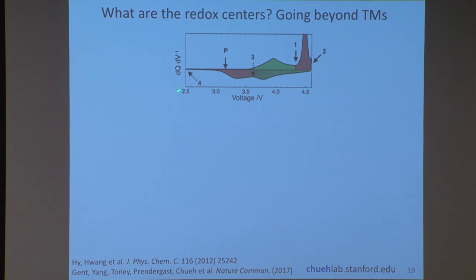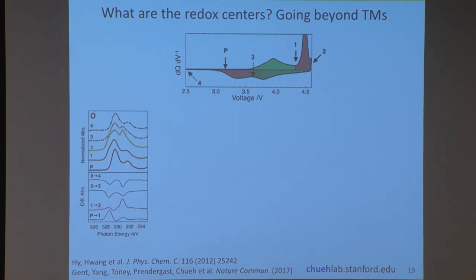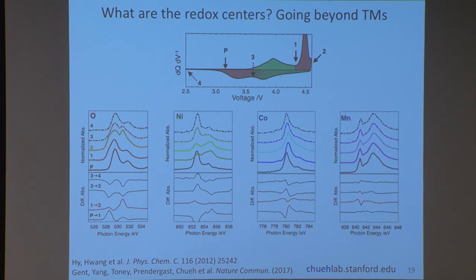This is basically looking at the single charge and discharge cycle of a battery, looking at where the electrons go. We use spectroscopy to see oxygen, nickel, cobalt, and manganese, and we actually find that huge capacity you get on the previous slide was actually due to the oxidation of oxygen. So we're able to oxidize oxygen, but without it leaving the material. This is quite unusual. Usually when you oxidize oxygen, it comes out as oxygen molecule, and this is highly undesirable.